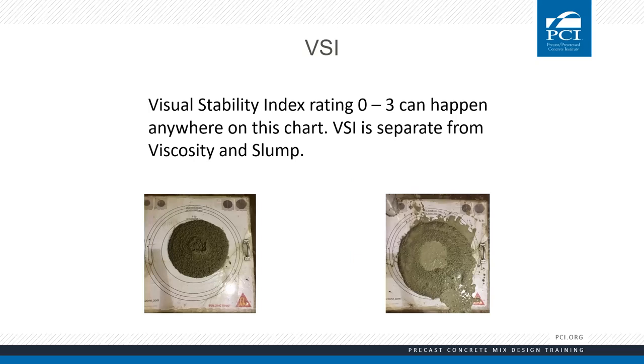The VSI — Visual Stability Index — has to be addressed. That's part of the ASTM standard for flow, and it gives us a clue to problems. The VSI is a daily QC assessment — every time you do a slump flow, you need to do the VSI. You assess it on a scale of zero to three and need to determine when you reject your concrete. Most people reject at three on the VSI. Maybe if it hits a two, contact quality control to determine if it's going to be a worse problem. You determine that for yourself.